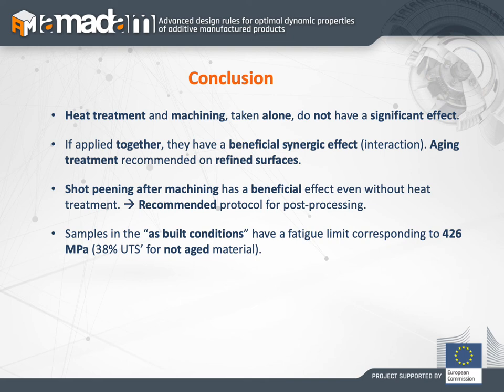In fact, for these samples in as-built condition, we have a fatigue limit corresponding to 426 MPa that is set at 38% of UTS first, that is the ultimate strength of the material before the aging treatment.